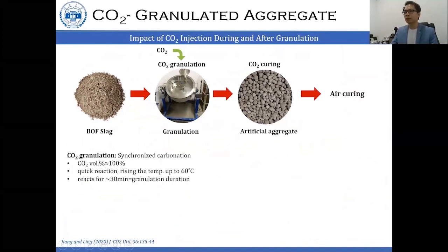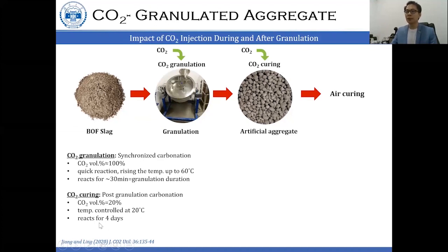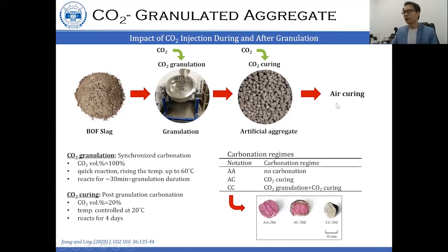So we apply CO2 during the granulations at the concentration of CO2 at 100% and run the granulation for 30 minutes. And after the granulation, we also can apply the CO2, or we put the aggregate in the CO2 chamber and keep the CO2 concentration at 20%, 20 degrees C, and exposure for 4 days. And after that, we have further cure under the natural air until 28 days for testing.